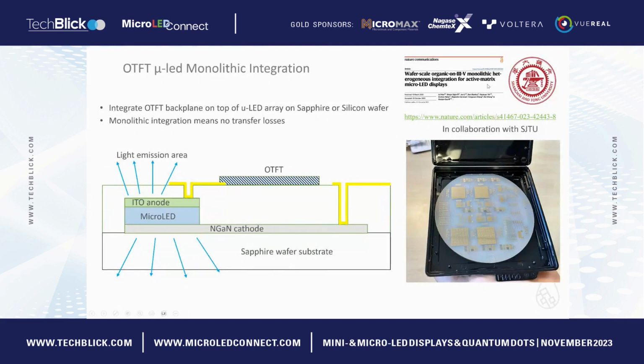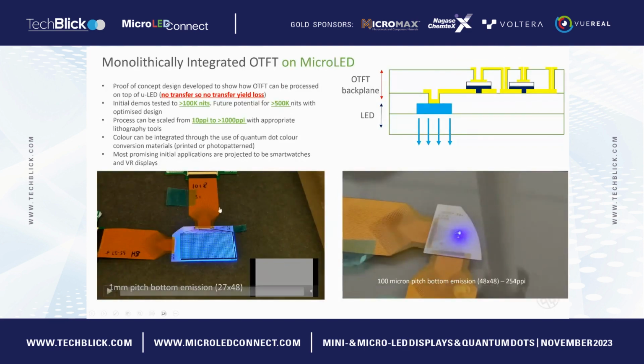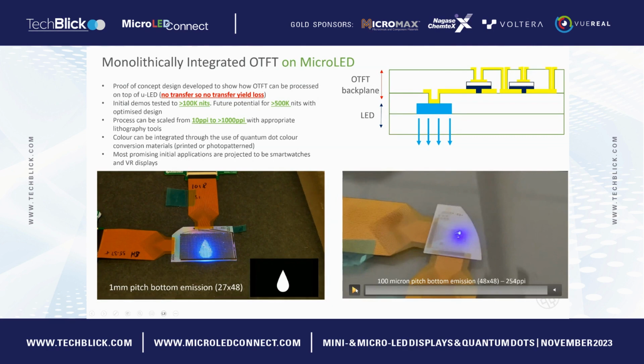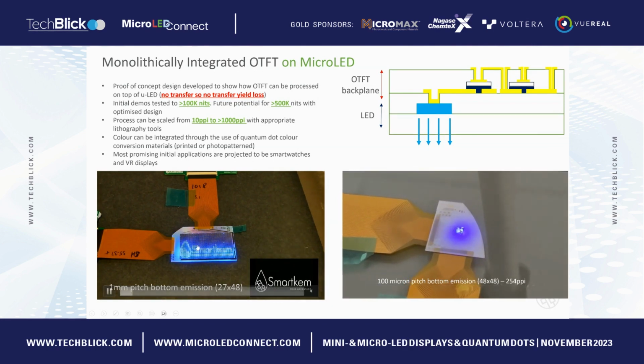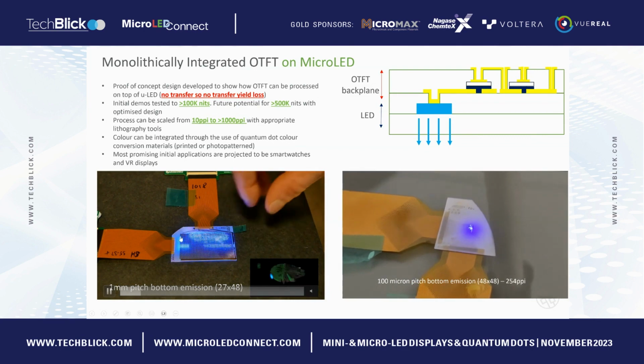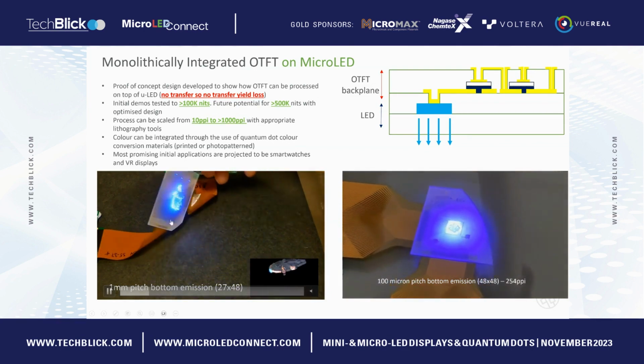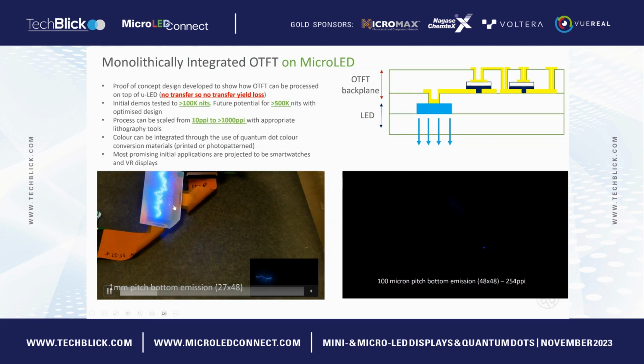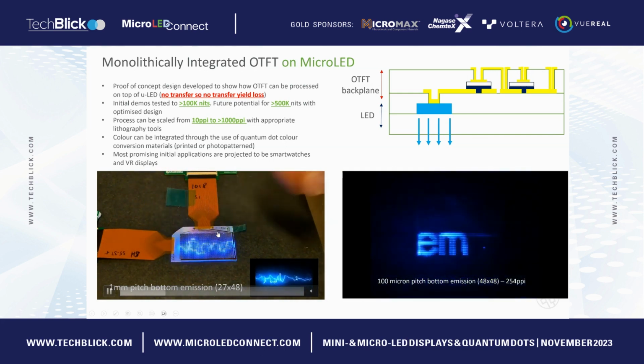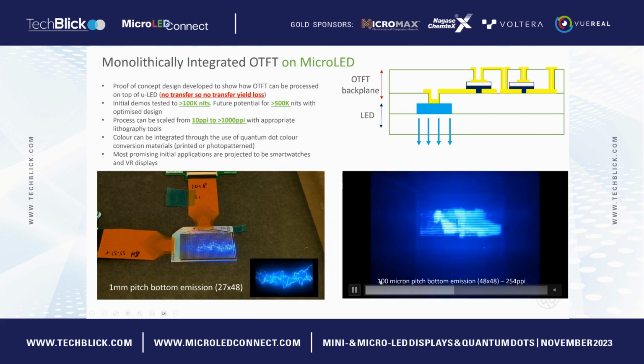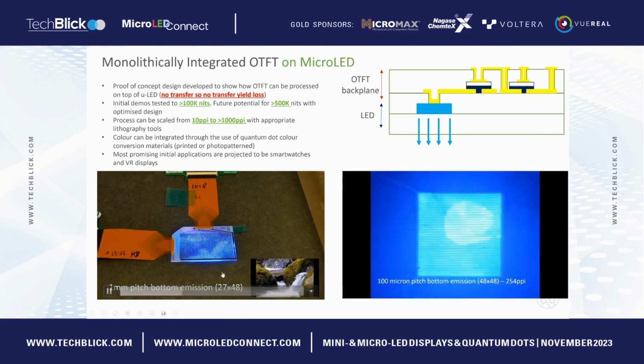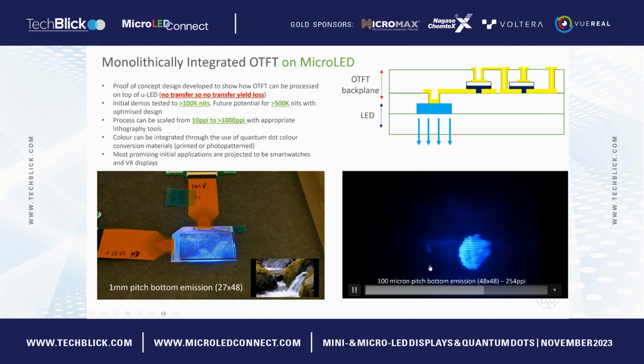And this is something we recently published in Nature Communications, which showed the fabrication of a range of different pitches of both mini and micro LED displays on top of the original native sapphire wafer. This shows a couple of videos. So on the left, we have a pitch of around about 1 millimeter. So it's a 27 by 48 display. It actually just emits light in both directions because it's on the original sapphire wafer. And the one on the right is a 100 micron pitch made on the same wafer, it's just a different parts of the wafer, and with the same process.